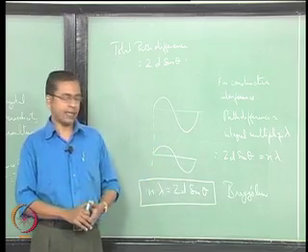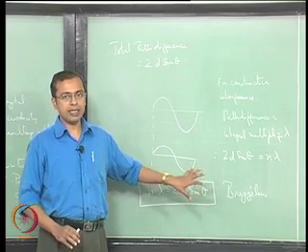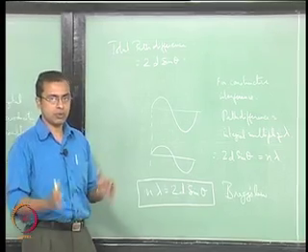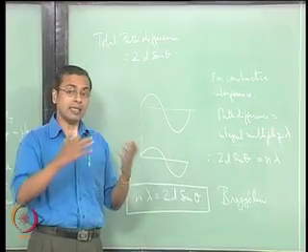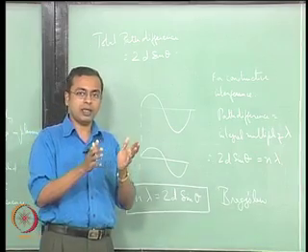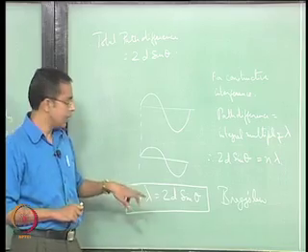The concept behind its derivation is valid, and in fact we are going to use essentially the same kind of approach even when we look at the reciprocal lattice representation of this interaction, but this is the way it is derived in real space. We are looking at real space planes and the interaction of waves as they interact with those real space planes. When they come off of those planes, how is it that they are constructively interfering, and when they interfere, what is the rule that has to be true for the interference to be constructive, and so that is how we end up with this n lambda being here. Okay, so this is Bragg's law.